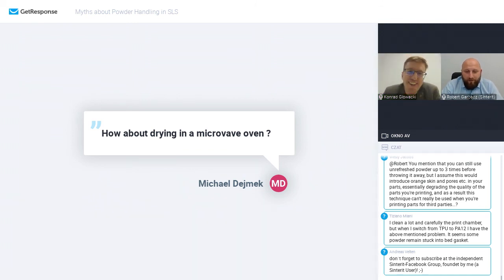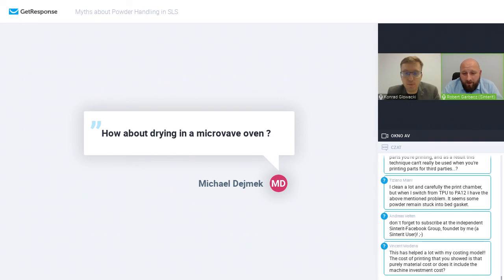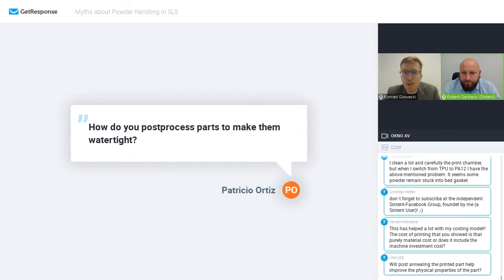Drying in a microwave oven is not a good idea, because the particles inside the polyamides are really tough to get out of the system. I think the microwave oven heats up from the inside, so it makes the powder melt. So I don't think you should use a microwave oven, or you can use it if you want to destroy the oven. A normal kitchen oven does the job. So no microwaving, please.